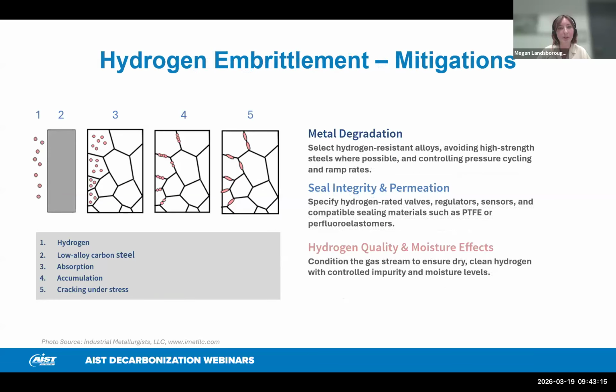Okay. And then if we want to take a look at the mitigations associated with these, for metal degradation, you want to select hydrogen-resistant alloys, avoiding high-strength steels where possible, and controlling pressure cycling and ramp rate. With your seal integrity, you want to specify hydrogen-rated valves, regulators, sensors, and compatible sealing material, such as PTFE. For your hydrogen quality, it's really important that you condition the gas stream to ensure dry, clean hydrogen with controlled impurity and moisture levels.